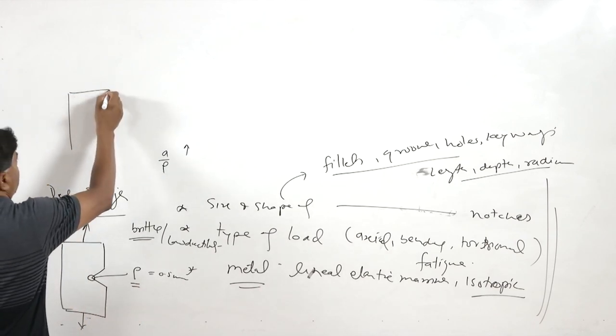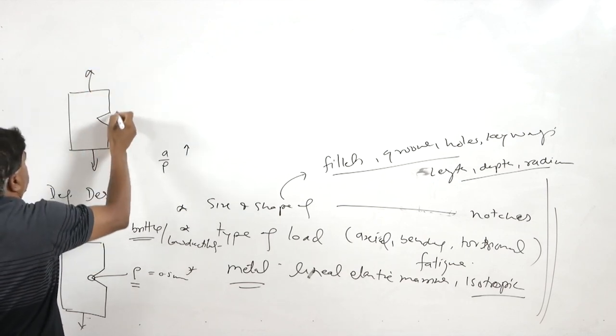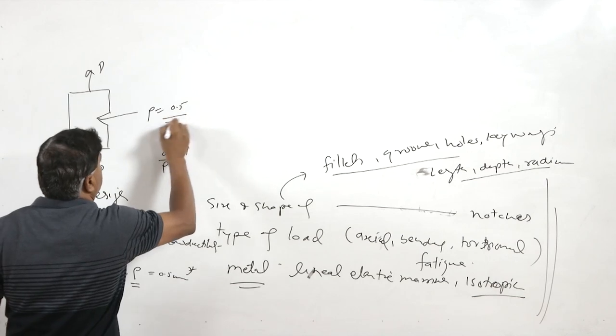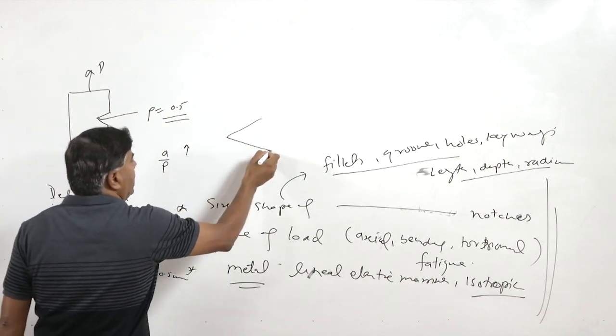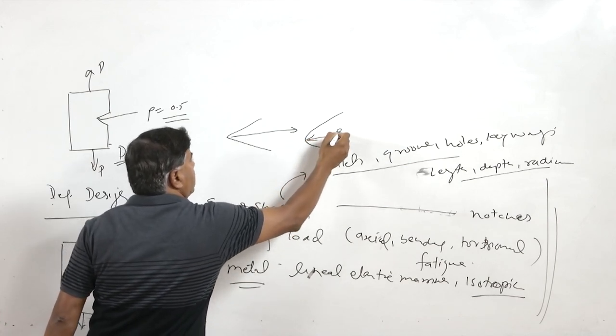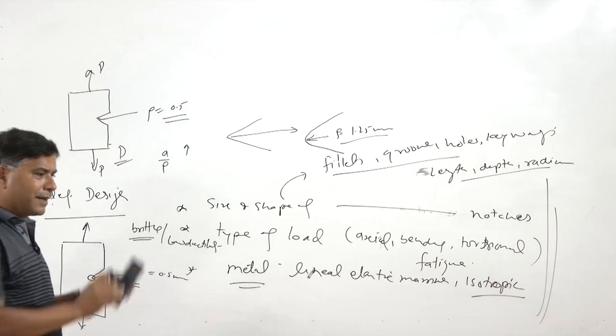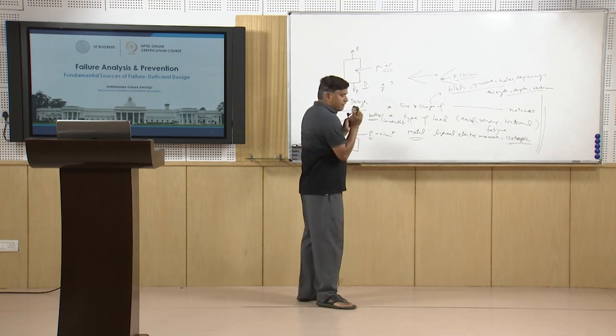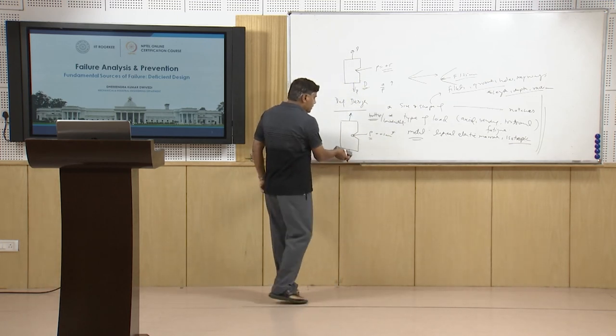In case of ductile systems, if the same geometrical feature is present as a notch with radius ρ = 0.5 mm, under external load conditions the crack tip will tend to get blunt. Blunting of the crack tip simply increases the nose radius — for example, from 0.5 to 1.25 mm — which leads to reduction in stress localization. The maximum stress at the tip of the crack will be reduced, lowering the tendency for nucleation and growth of cracks and eventually reducing the failure tendency.